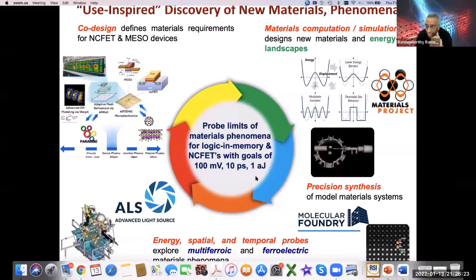We actually looked at this very carefully, before I went to DOE, when I ditched all of this stuff. If you look at photovoltaics, essentially all of them use a PN junction to do charge splitting. We said, why can't you use a ferroelectric surface potential to split it? It turns out it's a pretty large potential, and the efficiency is actually pretty high, but the quantum efficiency is the problem. The only problem is the carrier lifetime in bismuth ferrite is abysmally poor.